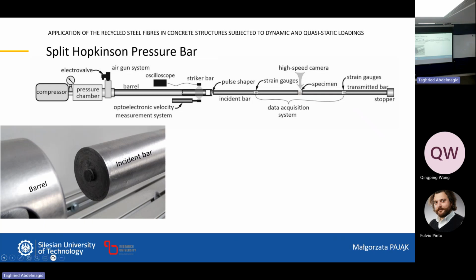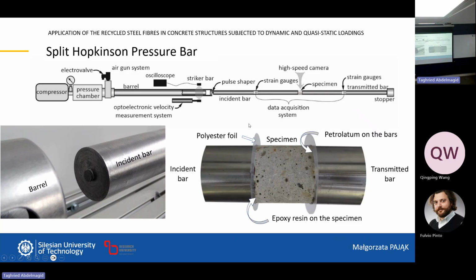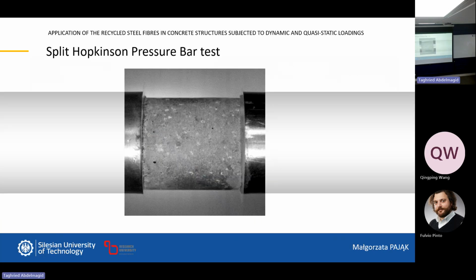So we have to choose the exact pulse shaper to get the right results. And the same, the specimen has to be prepared in a special way. We have to assure the exact adhesion of the specimen on both ends of the specimen area to the bars. If we don't get it, the results are rubbish. So here I would like to show you the test.